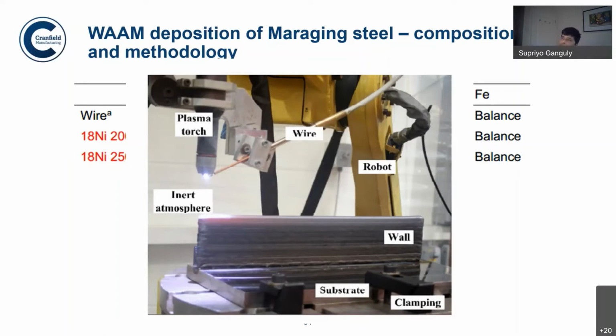And it is very important, because you cannot really build such a structure in a normal environment. The scale or oxide formation while you build will be tremendous, and that will change the surface tension of the weld pool and impact how the scale will be entrapped within some parts of the metal, which will increase the strength but reduce the ductility tremendously. There will be a lot of influence on the properties if it is done in normal shielding or a normal environment, which is beyond the control of an operator.